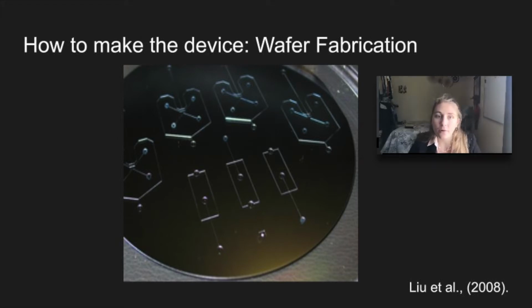This is a lengthy process and can take anywhere between 40 minutes and a couple of hours. Photolithography uses a photoresist, SU-8, and depending on the depth of the chambers of the device one is trying to obtain, a thicker or thinner photoresist can be used. The wafer is first cleaned using pressurized air, heat, and placed in a plasma cleaner.